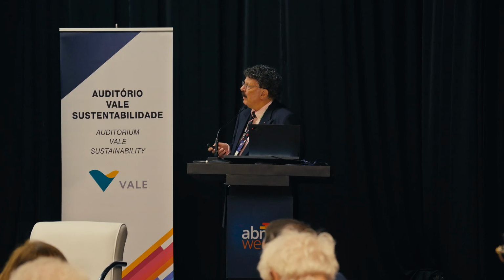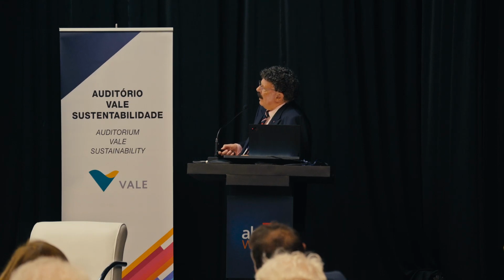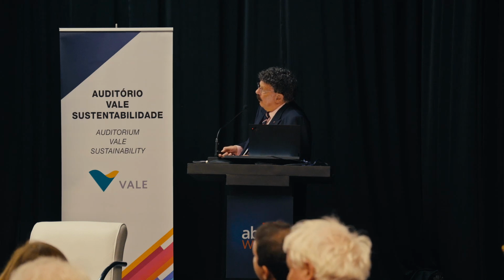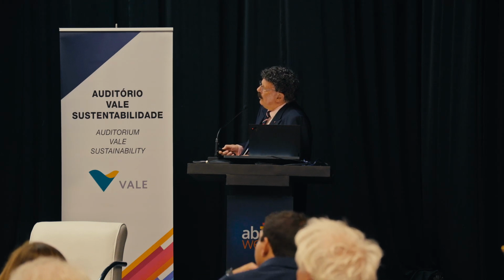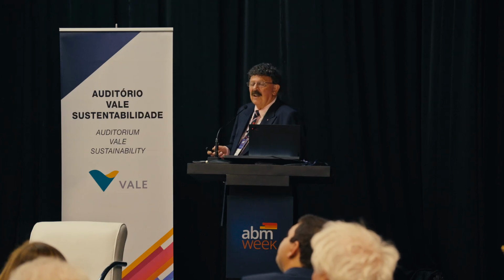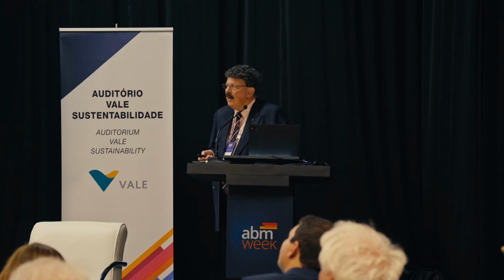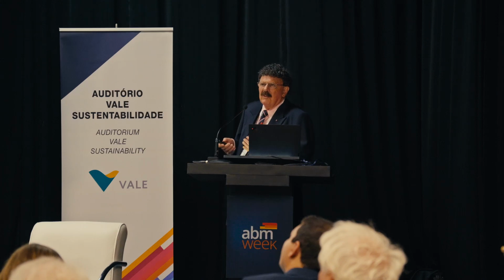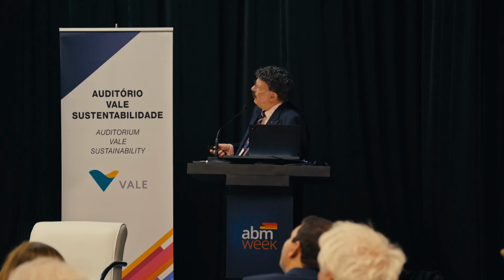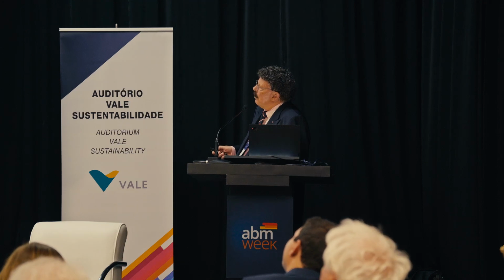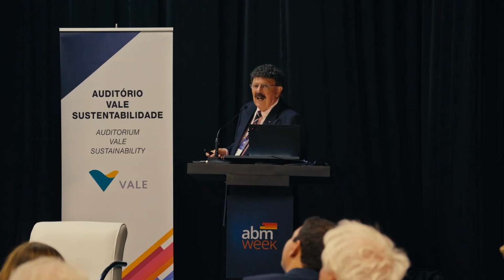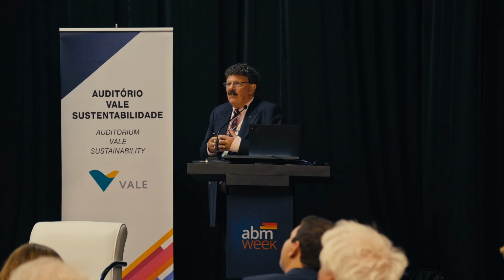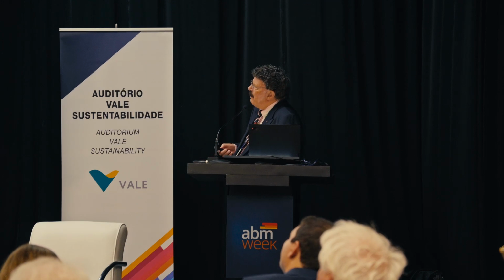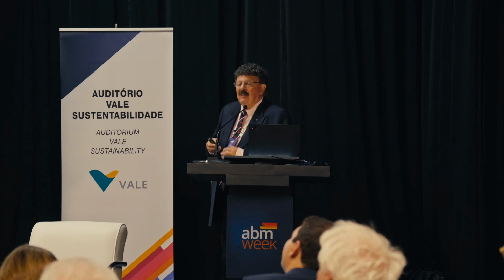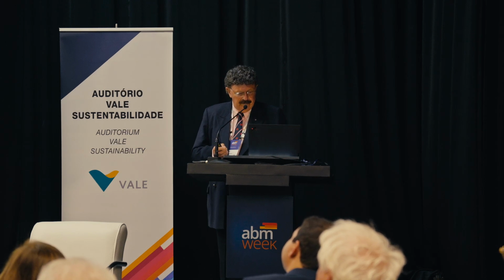But this is the kink band formation. And the kink bands look like this. They are basically where the material forms a kink. It basically moves to maximize the critical resolved shear stress. Interesting. And it's associated with multiple dislocation sources. In this case, we get 2 sets of dislocation motions. These are the 111, 110s and the 111, 112s. And they form in the boundaries. And they're so close together in the boundaries, you can't even see them separately. But that's the key for these mechanisms, that they form this additional deformation mechanism.